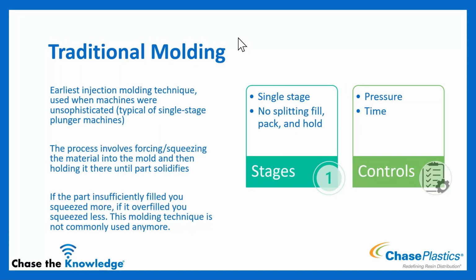So the traditional molding process, again, this is our earliest injection technique, unsophisticated machines, single stage plunger. And all we're doing is continuously forcing and squeezing material through that heated spreader and holding it in there until the part's solidified. If you didn't fill out your cavity, your only recourse is to squeeze more material in harder. However, that also led to quite a bit of what we consider overfilling or overpacking. You may see things like flash or dieseling, and those were really your only two knobs. Push it harder, push it softer.